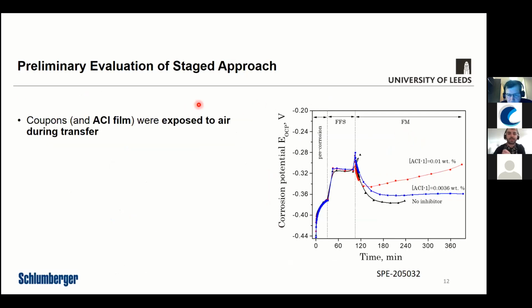So whilst these experiments were good, they showed a lot of potential for the staged approach. There was a couple of uncertainties just as a result of the method. So firstly, if you're transferring the sample from one beaker to another, you're exposing the coupon to air, the carbon steel coupon to air, and critically, also exposing the inhibitor film to air as well.